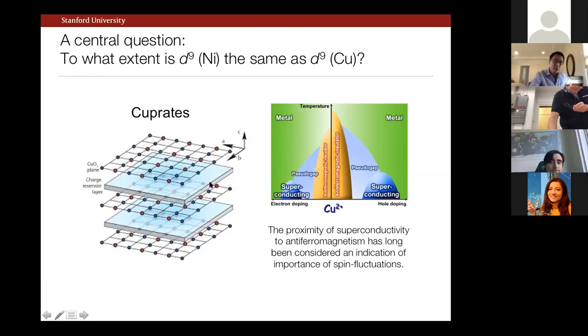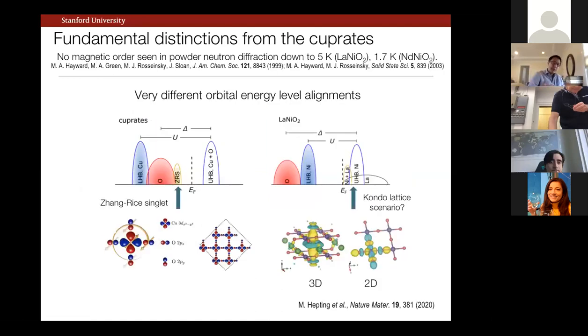The other thing that I'll come back to towards the end is that the crystal structure, again, is defined by copper oxide planes separated by so-called charge reservoir layers. This is where people, for example, do substitutional doping, and that charge is transferred, let's say, to the relevant CuO2 planes. So on the other hand, even though the structure and the electron configuration is the same, there are fundamental distinctions from the cuprates. One of them is actually back to these Liverpool studies, namely that they did powder neutron diffraction refinements, and they found no evidence for magnetic order down to about 5 or 2 Kelvin or so.